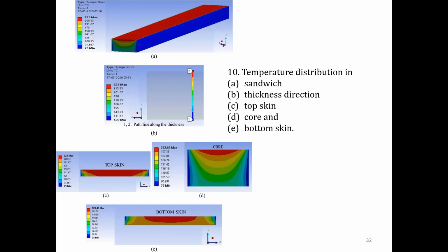The variation of the temperature in the radial direction is typically due to convective heat transfer at the lateral edges. It is seen in the core temperature as compared to the top skin, bottom skin, and also at the skin core interface. The bottom skin is in contact with the printer bed, which is maintained constant at 120 degrees C during printing.